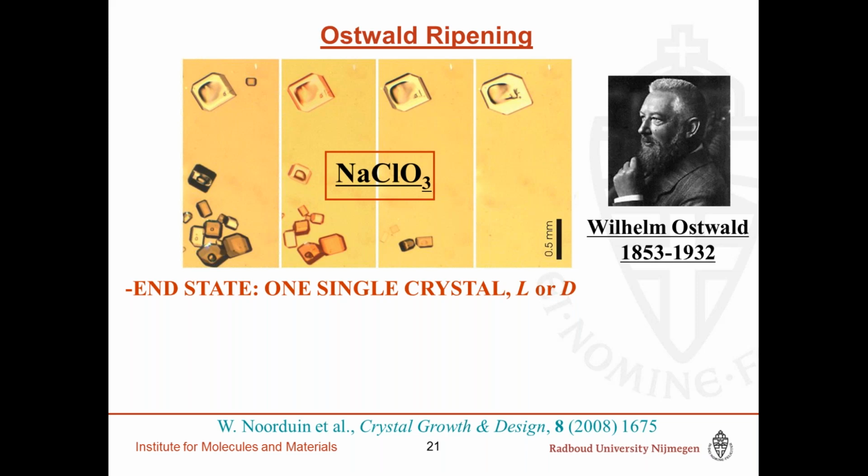Any tips for her? Yeah, well, the question there is again, and of course you do not know that, but the question is again, what is the phase diagram? Is the racemic conglomerate in terms of energy far away from the racemic compound, and perhaps also far away even from the amorphous material? That is very well possible, and in that case, energetics already make the nucleation of the conglomerate very unfavorable.